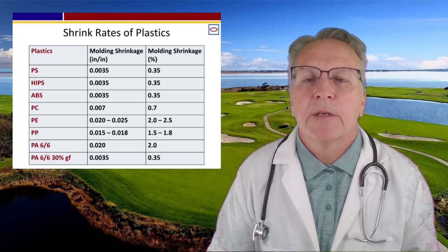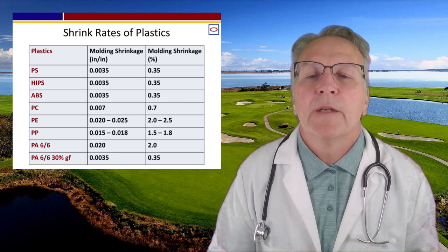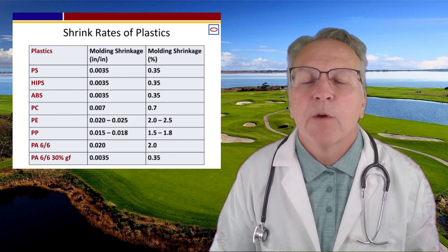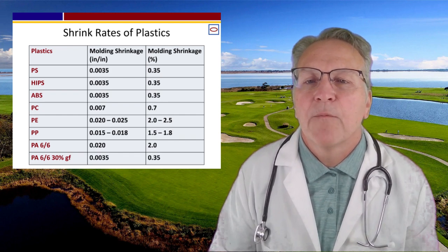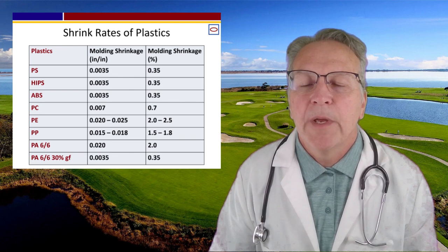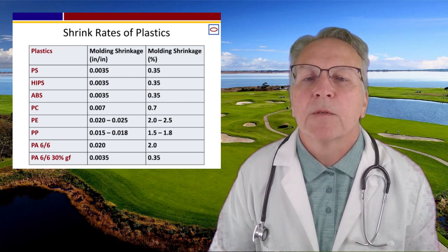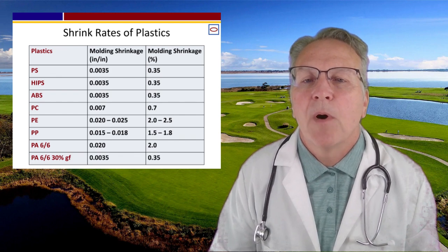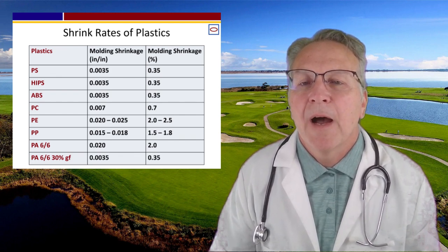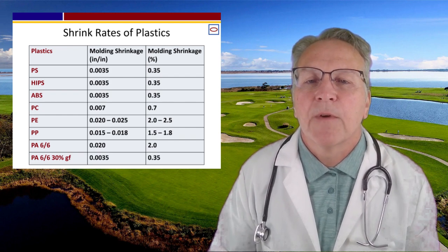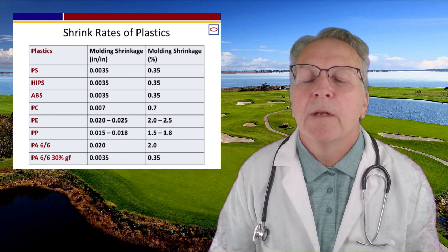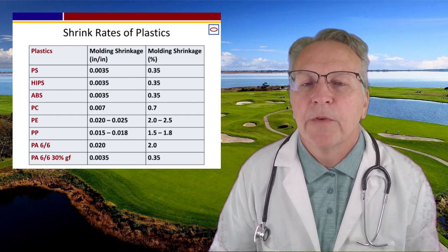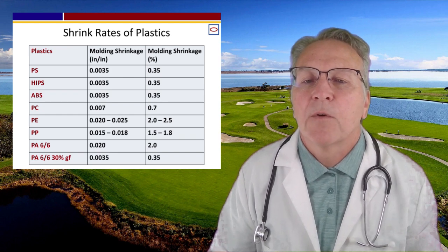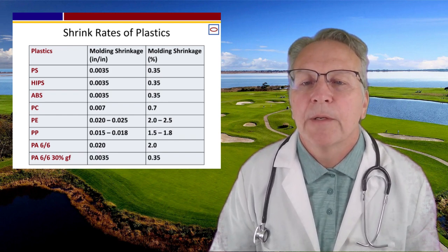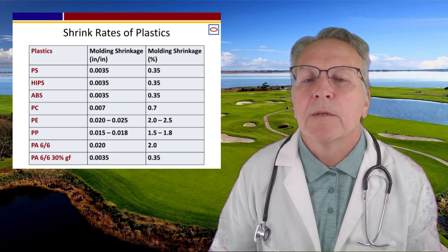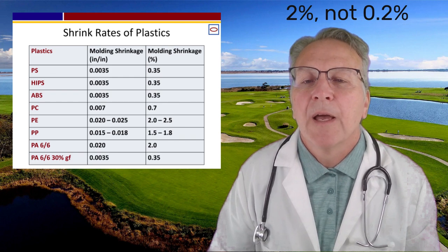Tool designers are challenged since amorphous and crystalline polymers have significantly different shrink rates as shown in the table. Amorphous plastics like polystyrene might shrink 3.5 mils or 3.5 thousandths of an inch per inch, and polycarbonate shrinks about 7 mils per inch of length. Crystalline plastics polymer chains get closer to each other, creating high density, and thus they have high shrinkages from the melt. Polyethylene shrinks about 20 to 25 mils, while polypropylene shrinks 15 to 18 mils, since high levels of crystallinity creates high levels of shrinkage. About 20 mils equals about 2% shrinkage for these olefins, as shown in the table.